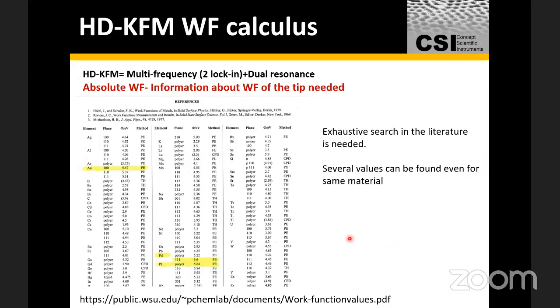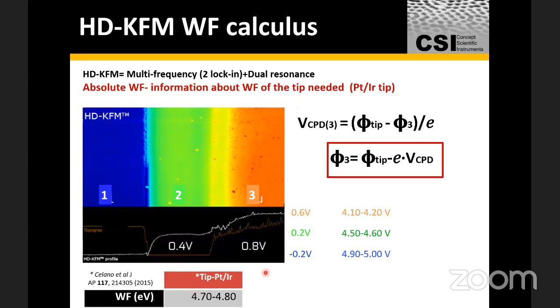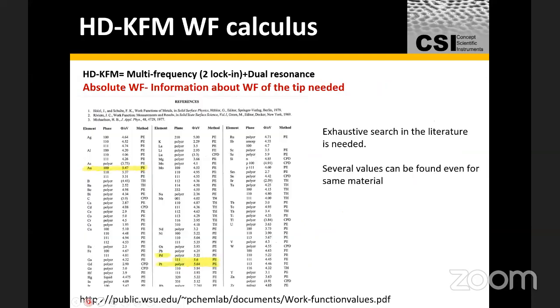So, when you're trying to get a numeric value on the work function of your material on the surface, you've got to know the work function of the cantilever itself. And what you've got to remember is that most of the values that are available are really for bulk materials. So there's obviously going to be some difference between the bulk work function of bulk platinum compared to what's coated for a few nanometers on the cantilever tip itself.